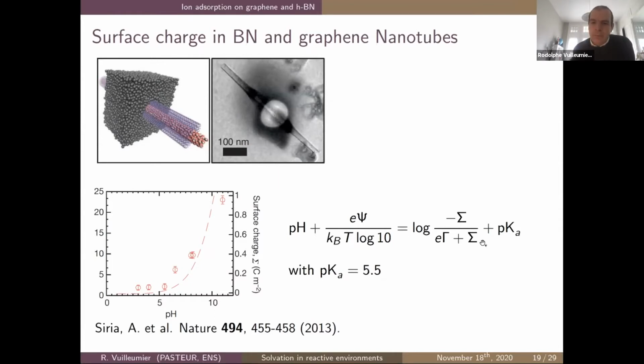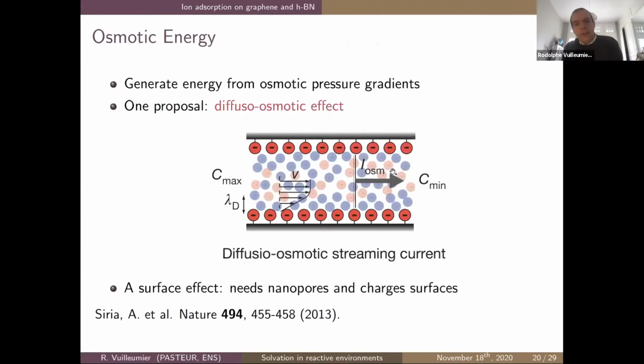And with a simple equilibration model, it relates to a surface pKa of about 5.5. So, a very strong adsorption of OH minus on these surfaces. This may have applications, for example, in blue energy, using here another phenomenon than the one that Laura alluded to. Here they wanted to use it for osmotic energy.